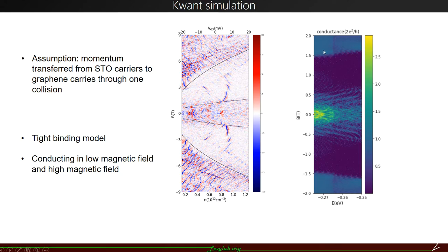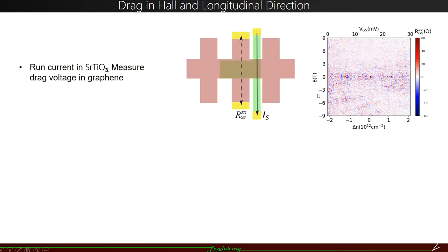So here we plotted the conductance as a function of magnetic field and Fermi level. So this is the result of Kwant simulation, and this is the experimental result. We can see that both of them show the conductance in the low and high magnetic field region, but not in the intermediate region. So if we make the assumption that the momentum is transferred from SrTiO carriers to graphene carriers through one collision, we can see that the transport properties in the drag layer mostly follow the tendency of the drive layer.